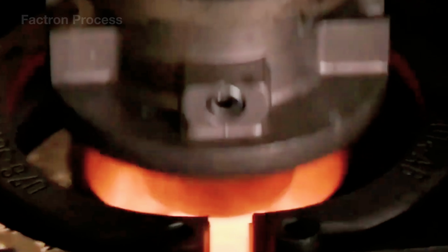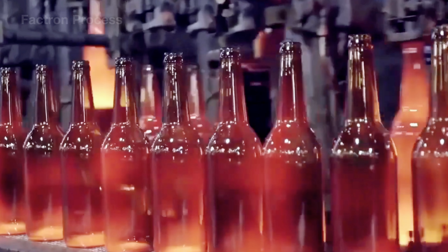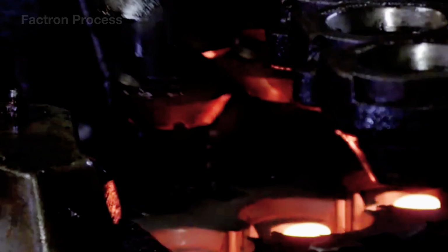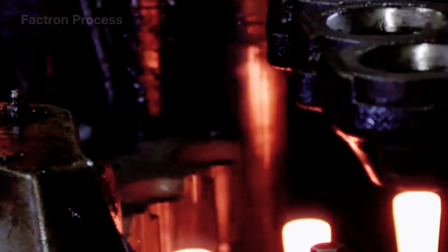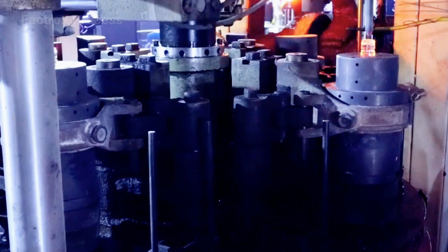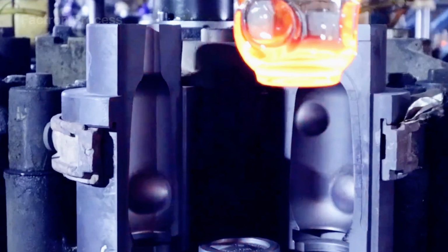From the furnace channel, molten glass is released as a continuous stream, then cut into separate drops called gobs. Each gob has a weight calculated according to the capacity and design of the product. For small bottles, each drop may weigh only a few dozen grams. For large bottles or thick jars, the weight can reach several hundred grams. After that, each gob falls into a heat-resistant steel mold.